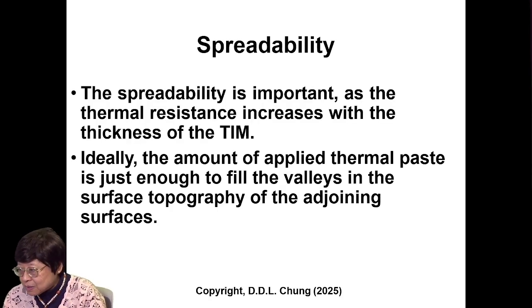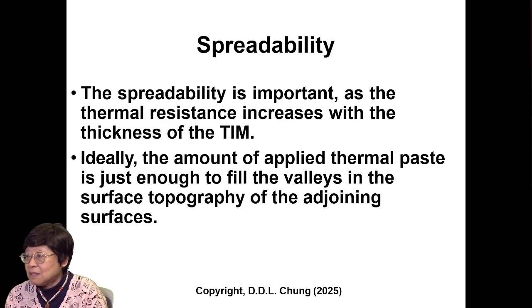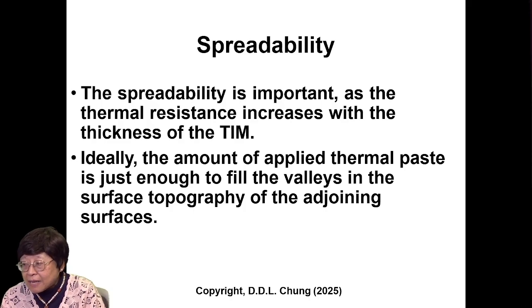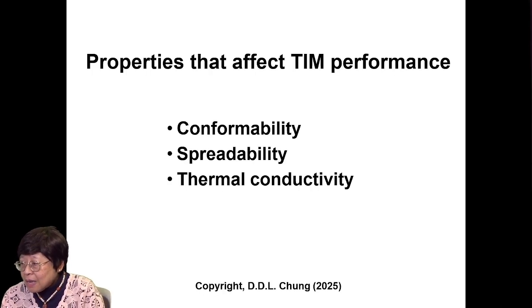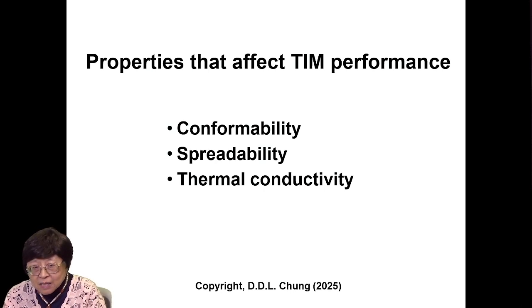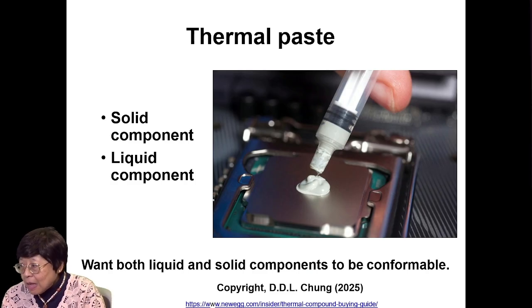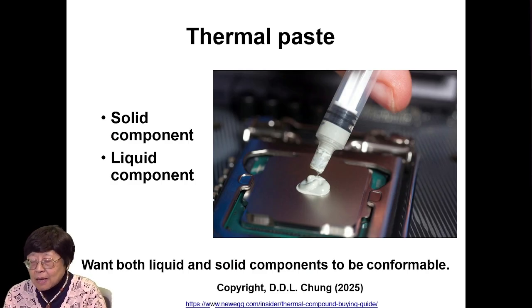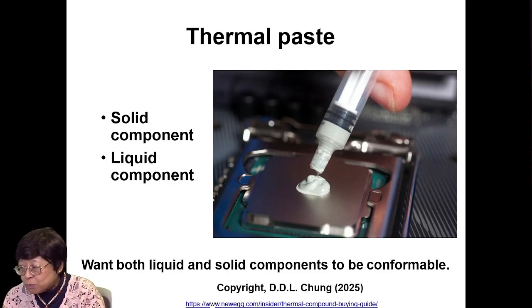Spreadability is also important as the thermal resistance increases with the thickness of the TIM. Ideally, the amount of the applied thermal paste is just enough to fill the valleys in the surface topography of the adjoining surfaces. Now, the properties that affect TIM performance include the conformability, the spreadability, and the thermal conductivity. The thermal paste has in it a solid component and a liquid component. We want both the liquid and solid components to be conformable.